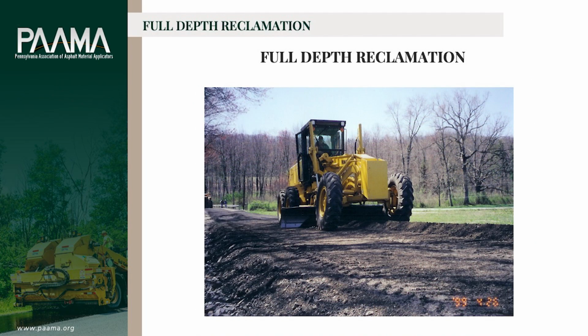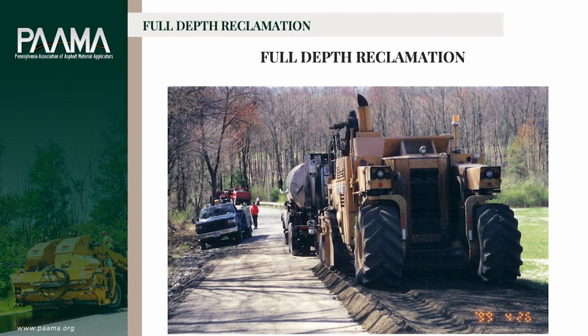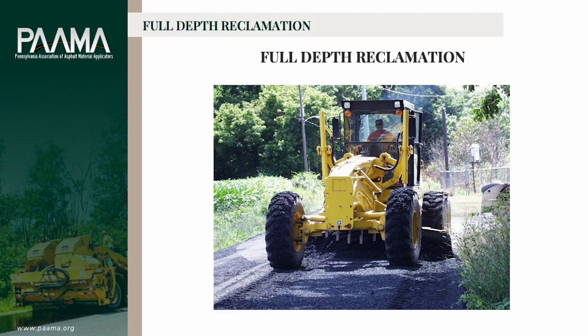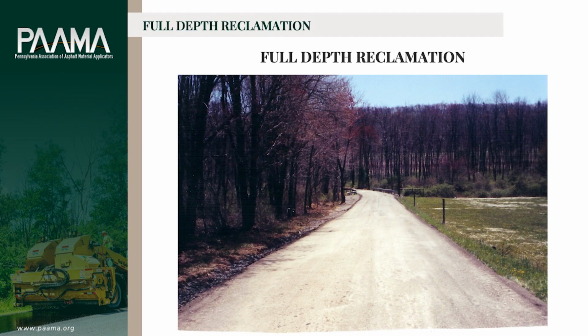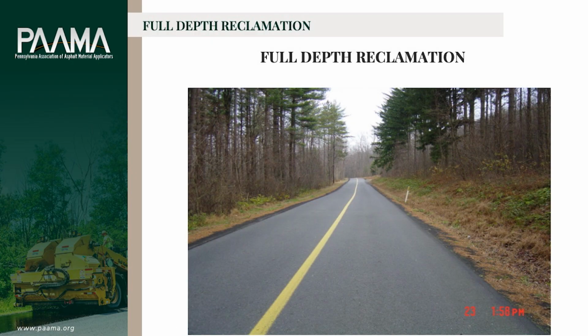The graders then regrade everything, getting everything graded. You can see the height they had to raise the road there by the shoulder. You can see how high that is, a couple of feet. And then, as I said, you're going to go through again, add the additive, mix it all together, do your grading and your fine grading, and compact the roadway, as we see here, a solid, nice looking roadway that's raised up several feet. And then a hot mix asphalt was placed on top, and that's the kind of road we produced.